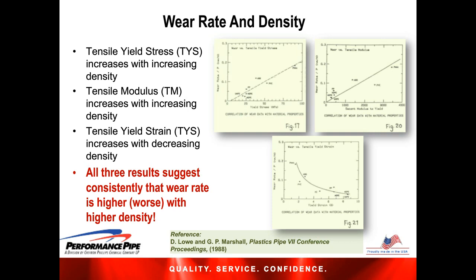And what we basically notice here is that each of these properties, the tensile yield strength, the tensile modulus, or the tensile yield strain, is basically directly dependent on the density. And if you take the composite analysis of what these three charts are telling us, all three results suggest consistently that the wear rate is higher, or worse, with higher density.